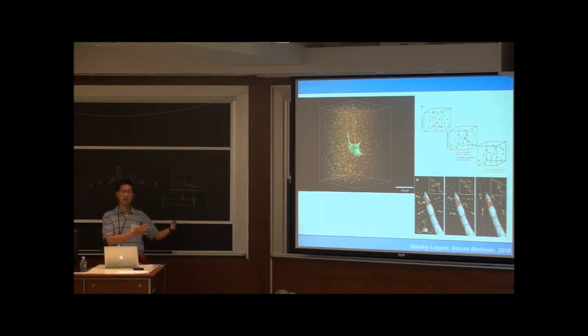And then you do the same after the strain has been removed. And what you find is that the shapes of all of these different structures, that are due to the just random position of all the beads, every shape is unique. And so from that, you can sort of find out how to register the 2 images and find the strains. Once you have the strains, then you can start to calculate the stresses.